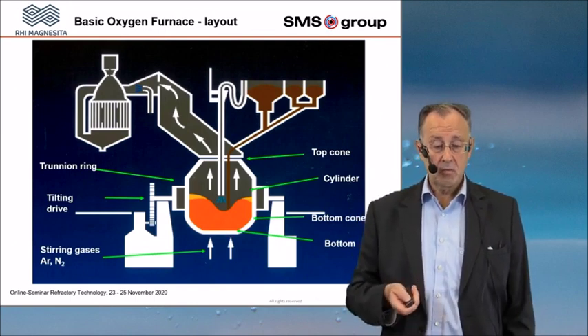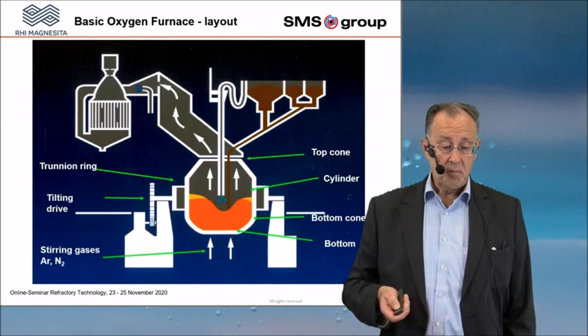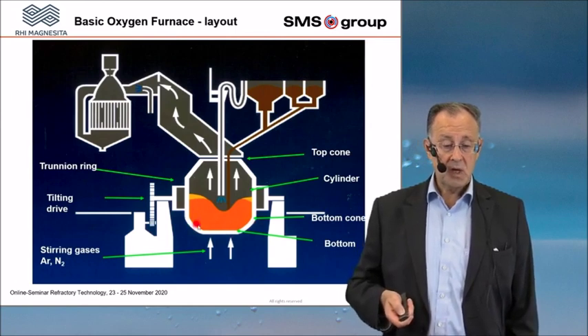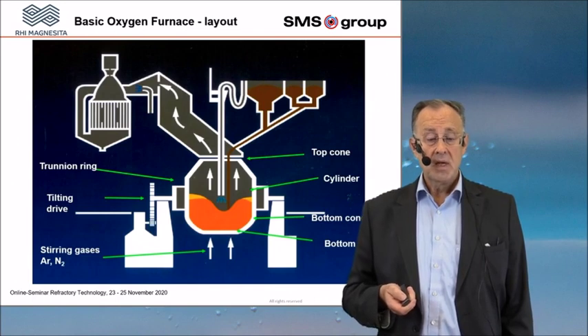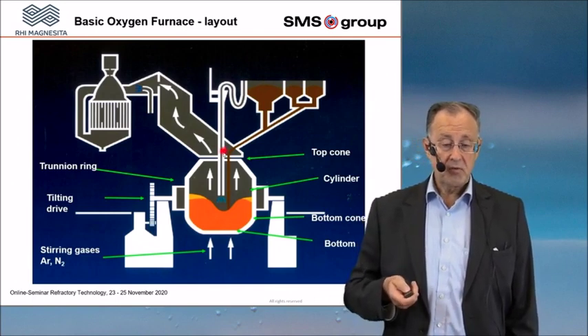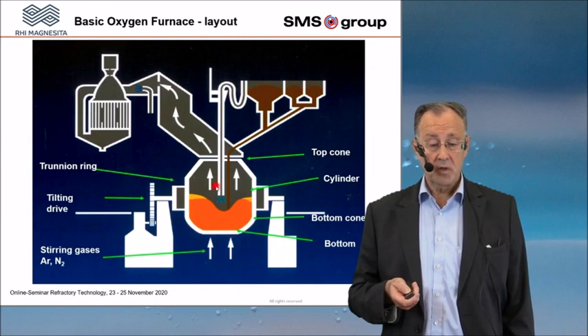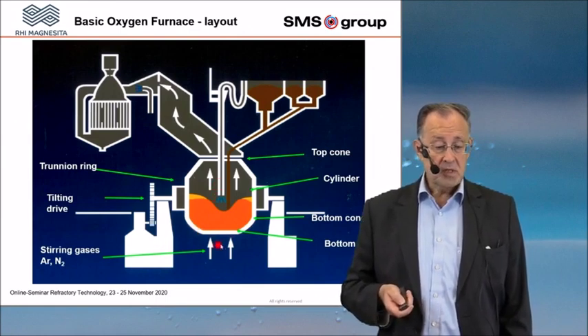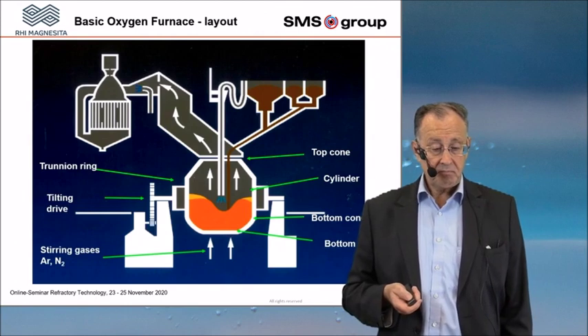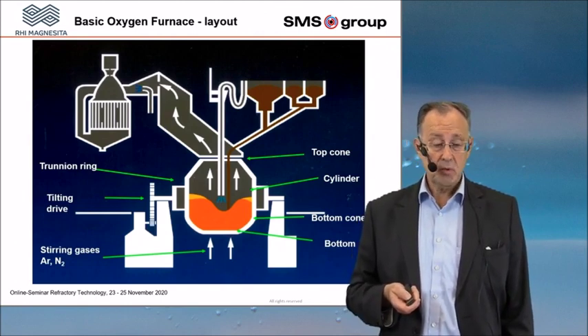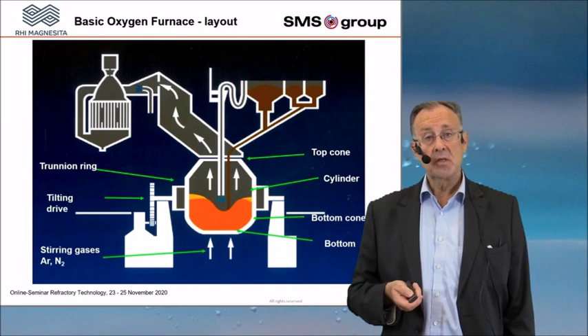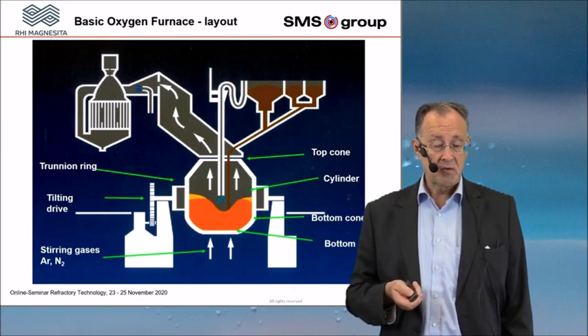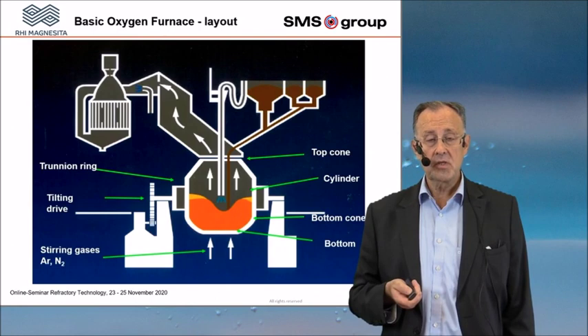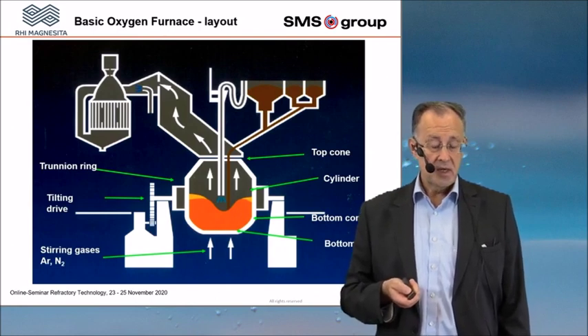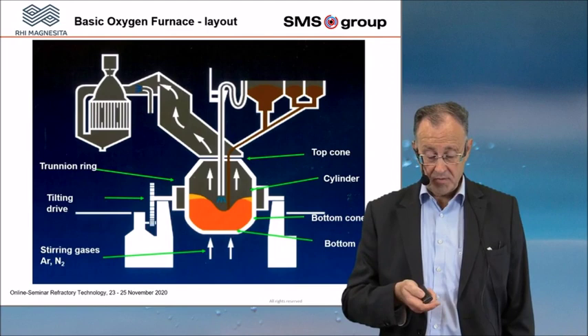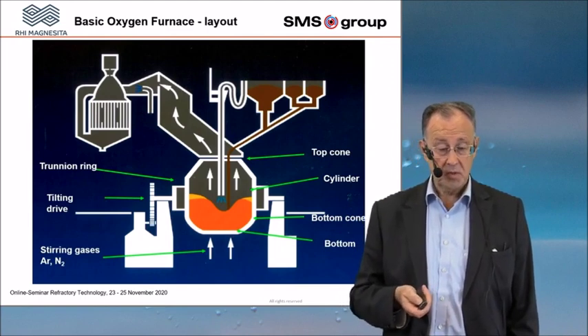Other converters have a complete vessel without a replaceable bottom. Then it means that you have to put all your refractory material from the top into the converter for the relining purpose. The bottom is equipped with stirring plugs, so that you can stir during the blowing process. Normally you use nitrogen, and in case you have steel grades with a very low amount of nitrogen in the analysis, you can use argon. Later on I will explain why it is so important.